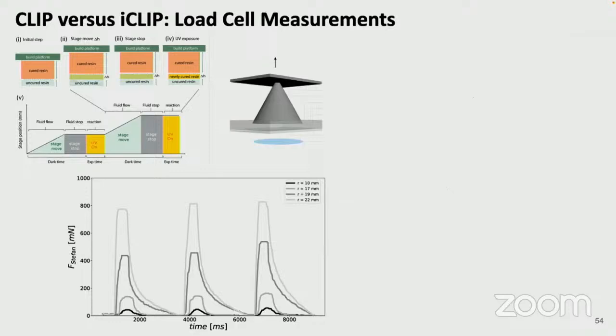But the most important thing about this process is this Stefan adhesion force. If you have two plates of glass and you have a drop of water between them, it's hard to pull the glass apart. It's easy to slide them. But we're basically pulling in the Z direction two solid surfaces with liquid between them. That's what draws the liquid in. There's a lot of forces on the part. So much so that you have to balance that with the simple work of adhesion of the part glued to the platform. And if the adhesion between the part and the window caused by that liquid gap exceeds the work of adhesion in that area, the parts can fall off the platform, a failure mode.